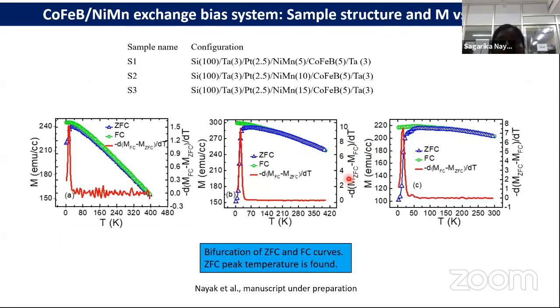Next, I'll move to my next topic, the cobalt iron boron nickel manganese exchange bias system. In this chapter, I will describe the nickel manganese thickness, which increases from 5 to 15 nanometer, with a fixed cobalt iron thickness of 5 nanometer. Again, to reduce lattice mismatch, we deposited tantalum and platinum as seed layers, and then deposited nickel manganese, and we performed measurements to know if there is any phase transition present in the system or not.